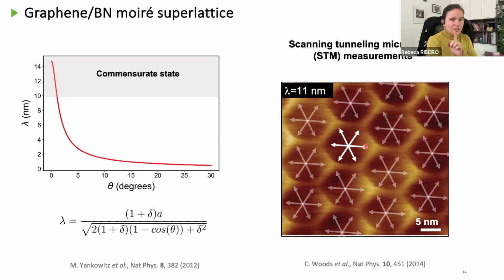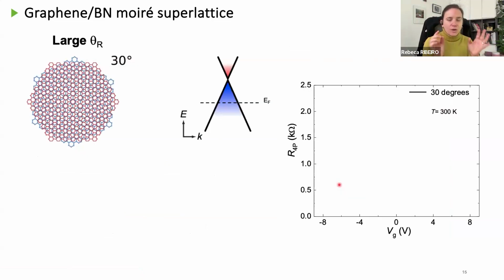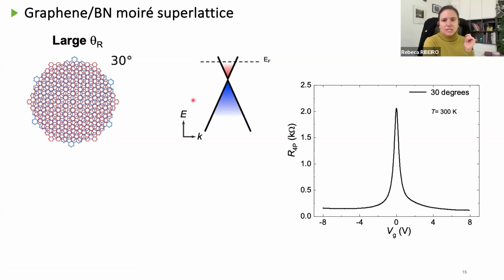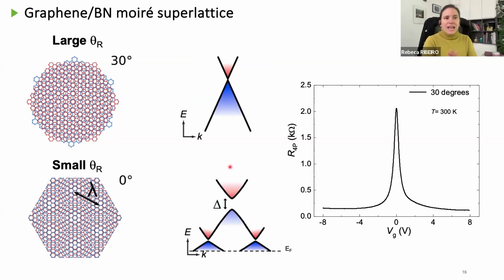So let's go one slide more and then I go for questions, because I saw that I have a comment. So let's go back to our previous example where we are measuring transport. We are measuring the resistance as a function of the gate voltage or the position of the Fermi energy. As I told you before, the example I gave you at the beginning was graphene on top of boron nitride, for example, and we are completely misaligned, so 30 degrees. And we have the same linear energy dispersion as we saw before. Now, as I told you already, we will have a strong increase of the resistance close to the charge neutrality point. If we realign the system, we will modify the electronic band structure.